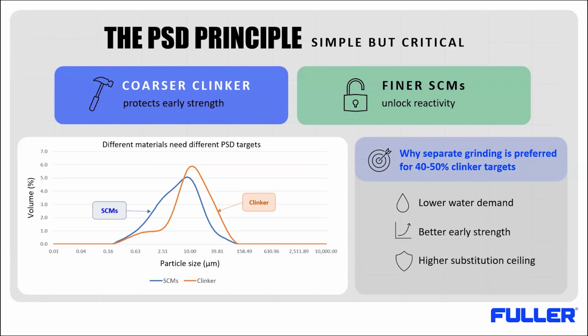When everything is ground together, the plant may compromise both sides. Softer material can be overground and increase water demand, while harder clinker may remain underground. That's why separate grinding, or at least better controlled grinding, becomes important at 40 or 50% clinker. The objective is not just to chase one Blaine number. The objective is to control the right PSD for each component.